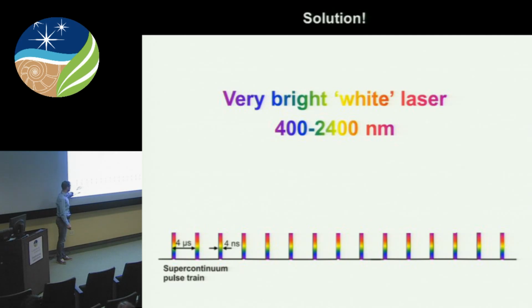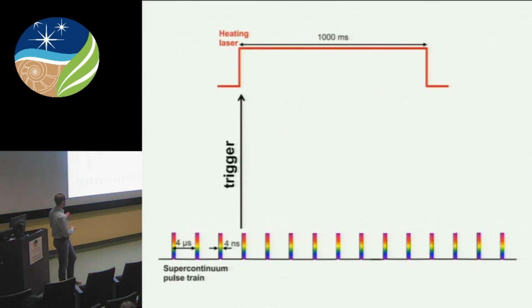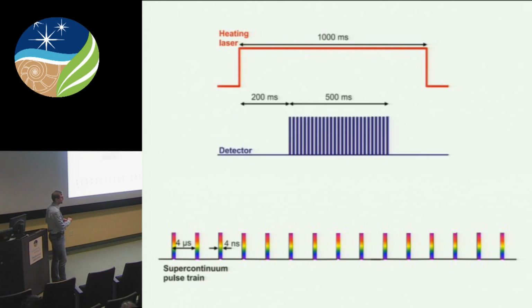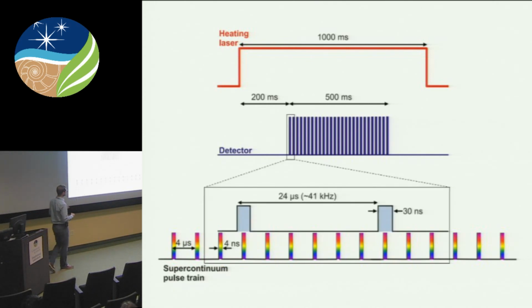And that's our solution to this problem. At the heart of the solution lies what we call a supercontinuum, or simply a white laser, that has a continuous wavelength distribution from 400 to 2400 nanometers. Importantly, it is a pulse source, and we can time it in principle as we want. But what you have to remember here is that the pulses are really short compared to the duration between the pulses. In this particular case, we have 4 microseconds, where 1 microsecond is a millionth of a second, between the pulses.